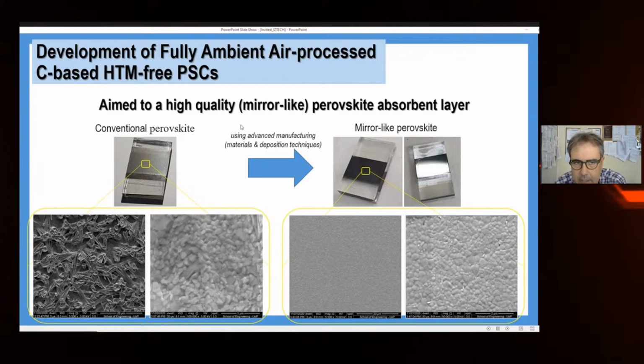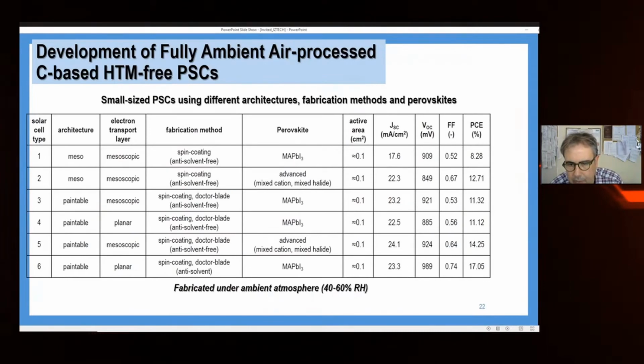So it is very important when we develop ambient air processed technology, perovskites in these conditions, to make the right inks of perovskite in order to be stable under uncontrolled air processed methods. Some typical examples of the efficiency that we can obtain with spin coating, but with special inks developed for ambient conditions. I will refer only to the last one, which is here. It is a really very efficient device made completely under uncontrolled ambient conditions.